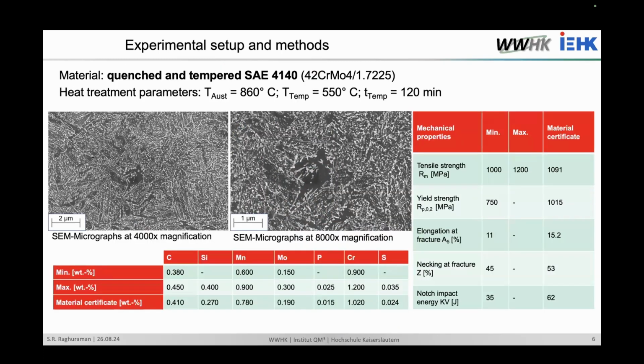The material that we have used here is quenched and tempered SAE 4140 steel. It is widely used in automobile components like crankshafts, gears, etc. It was heat treated at an austenitization temperature of 860 degrees Celsius, then quenched, followed by a tempering process at 550 degrees Celsius for 120 minutes. That is how we get the mechanical properties and the chemical compositions that I have tabulated here. The result is a very typical relaxed martensite microstructure that we can see in the micrographs.